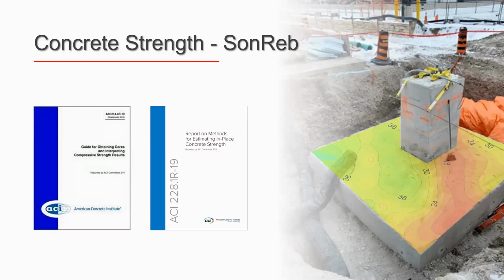Now, no coring was permitted, so absolutely there was no way to take concrete cores. So we performed Schmidt hammer test and UPV test, and we combined the results together using mathematical formulations, and we came up with a map of strength variation. This helps you see if a large area of concrete meets the minimum requirements of concrete strength or not. So if you have a 30 MPa design consideration and you are at 25, then this technique can actually help you identify the locations that might potentially be substandard.